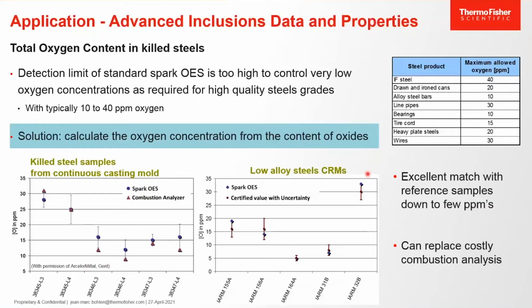On the right side, we have measured certified low alloy steel samples. So we compare the Spark OES result in blue with the certified value of the samples. And here again, you can see that for all the measured samples and down to a few ppm, there is an excellent match with the reference. So, very interesting. The standard method for this kind of analysis is normally combustion analysis. And we see here that optical emission offers an interesting alternative, a good candidate to replace this costly kind of analysis.